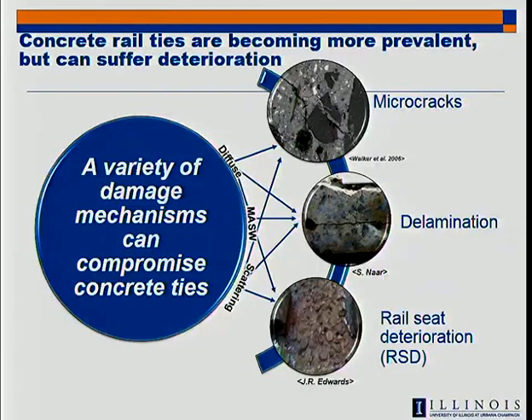But there are other mechanisms where a discrete defect could occur. So for example, the prestressed tendons in the concrete ties can corrode. And when they corrode, they expand, the rust around them expands, and it can push out, and it can cause a very discrete crack. So now instead of distributed microcracking, we have one flat, discrete crack that maybe runs parallel to the tendons that are corroding. That's called a delamination. So those kinds of cracks can also occur. It's a different kind of mechanism.